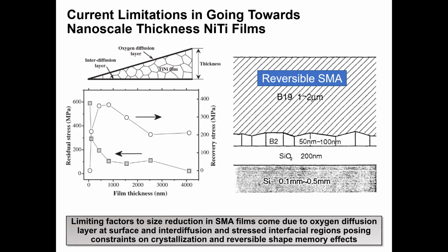So also, if you focus your attention on this graph of recovery stress and residual stress versus the film thickness, you'll see a couple of results that highlight these limitations. The recovery stress reaches some maximum value as the film thickness is reduced, and this is typically around 700 nanometers to a micron in film thickness. And for films thinner than this, the recovery stress plummets extremely sharply or vanishes altogether in nanoscale thickness films.